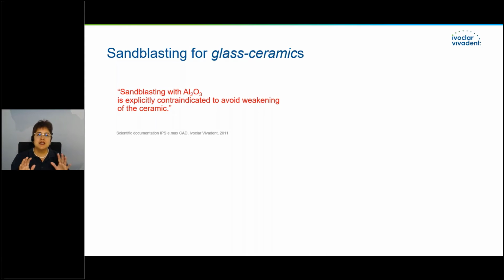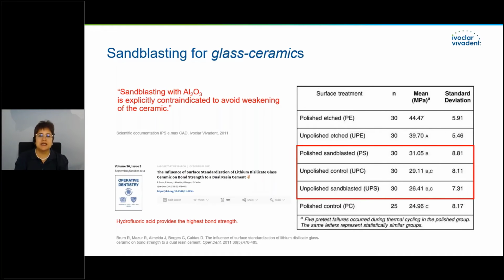So let's look at some studies, and they say that sandblasting is not suitable for glass ceramics, otherwise you will weaken the glass ceramics. With sandblasting on ceramics, you will leave micro cracks, and these micro cracks can propagate over time, and it could end up with a fracture. So at the end, you will lose the restoration. And even more important, with sandblasting of glass ceramic, you will not improve the bond strength. Maybe you will think, oh, with sandblasting, I will have higher bond strength. This is not so.